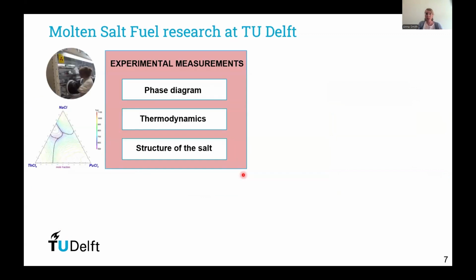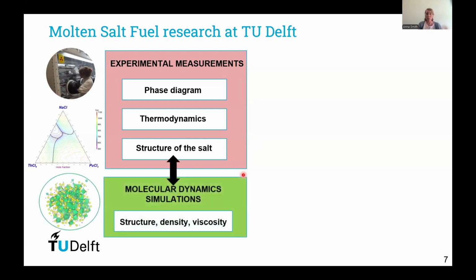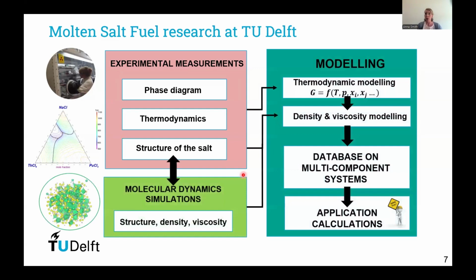Our approach in Delft is to perform some experimental measurements of phase diagrams, of thermodynamics of the systems. We also look at the structure of the salt, and we couple this with molecular dynamics simulations to get more insight into the structure of the salt, into thermophysical properties such as density and viscosity. And once we have this information from experimental measurements or from simulations, we use that as input to develop some thermodynamic models as well as density and viscosity models that are coupled to the thermodynamic assessments.